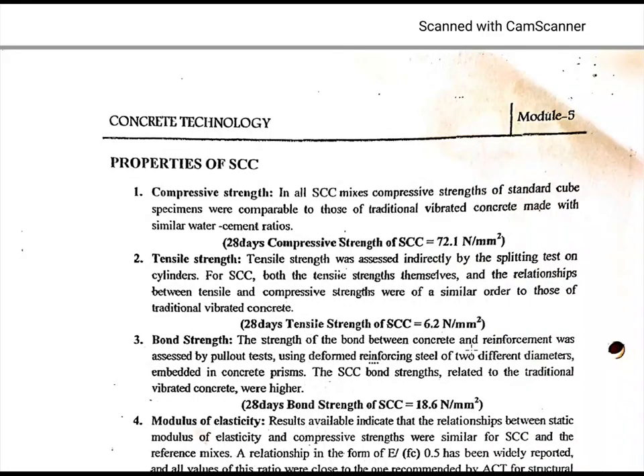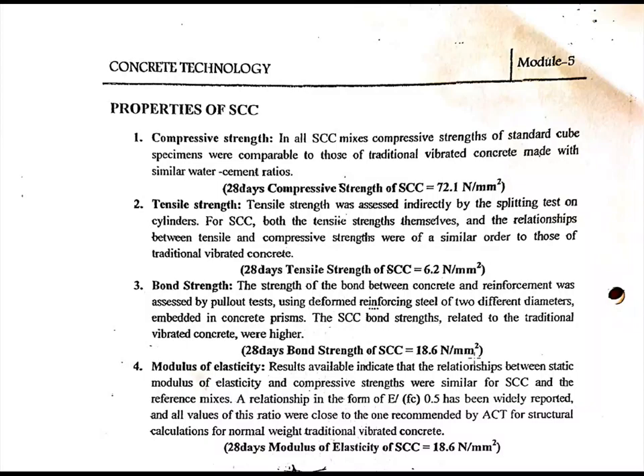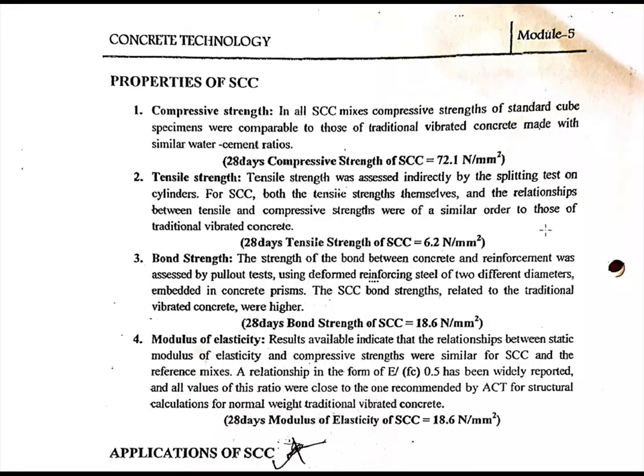Okay, so this is about the tests on self-compacting concrete. There are a few comparative properties of conventional and self-compacting concrete. In all SCC mixes, the compressive strength of standard cube specimens was comparable to those of traditionally vibrated concrete made with similar water cement ratio. With the water cement ratio the same, to achieve compressive strength, we used vibrators or some compaction devices. Here we have not used any compaction devices. Even though we have not used those compacting devices, we have achieved around the same strength without doing any compaction.